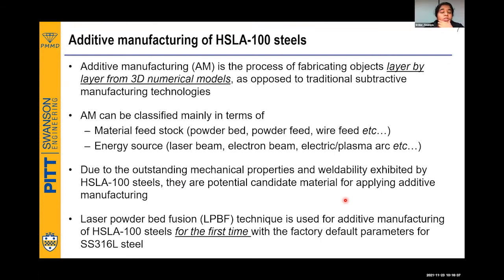So what we have done is we used the laser powder bed fusion technique for fabricating HSLA 100 steels for the first time. This is a new material for which additive manufacturing is being applied, and we are doing it using LPBF, which no one has done for this material. So we really don't know what parameters to use.